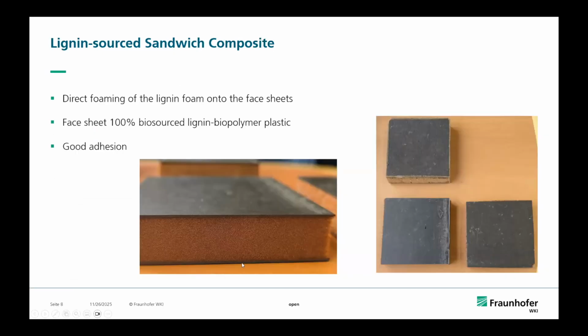And the second example is that we make a lignin-based sandwich composite. We prepared these by directly forming the lignin foam onto a face sheet. And these face sheets consist of 100% biosourced lignin biopolymer plastic, which can be prepared by an extruding process. The interesting fact here is that we really can form it on these sheets. So this doesn't require any separate adhesive, so it will directly adhere to this material. That is actually very convenient.